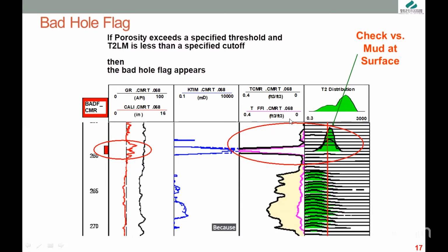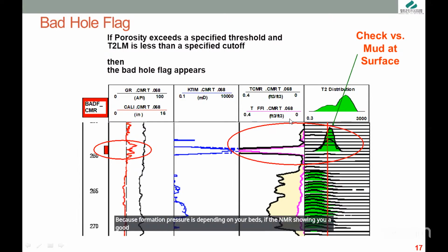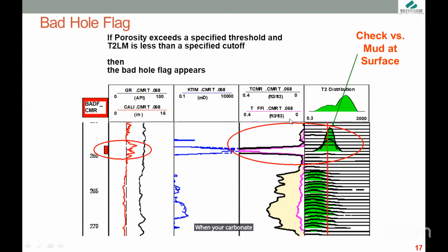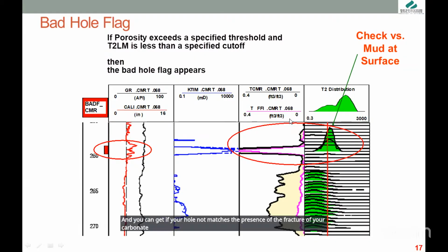Because you will find this issue, I think, only in carbonate or very tight sand. And in very tight sand, I didn't expect good permeability. So I think this is carbonate, right or not? In case of carbonate, don't depend on formation pressure, because formation pressure depends on your beds. If the NMR shows you a good permeability, now you have caught a good permeability. The RFT in this case depends on the probe suction time, and actually it estimates the total permeability or the vugs present in your carbonate. And if your hole doesn't match the presence of the fractures in your carbonate, now you will always find the RFT will be tight.